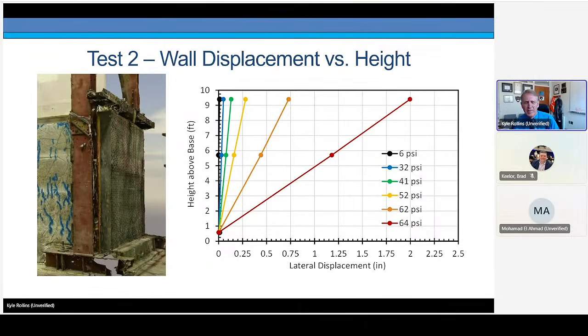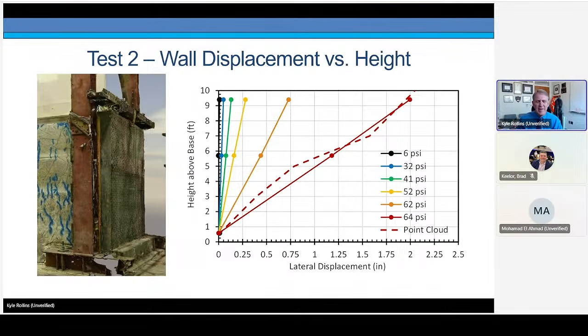This plot shows the wall displacement versus height that's measured by the string potentiometers on that concrete wall face. And you might notice that we can get clear up to maybe 52 psi of surcharge pressure before we get more than a quarter inch of lateral displacement. So the wall is really helping reduce the displacements that take place here. And then as we go from 50 to 60, we start to get a lot more deformation, and it's rotating about the base as we would expect. And we can look at the displacement that we calculated from the DIC system, and it's fairly similar. The DIC also told us that the wall is failing pretty uniformly from side to side, which is what we wanted to see.